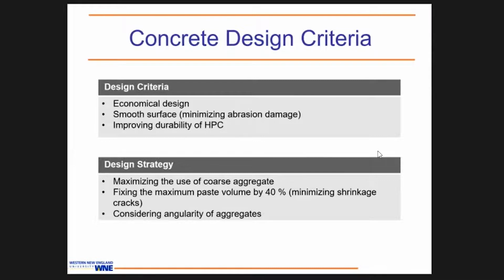So I dropped the ultra. We are not shooting for 20,000 PSI concrete. Again, if you are going there, you have to get rid of all the coarse aggregate. If you are using only fine or those cement type powders, your cost is going up significantly. In order to keep our concrete economical, we have to use the coarse aggregate in some amount. So that's why we call it just high performance concrete. So the design strategy is to maximize the use of the coarse aggregate.